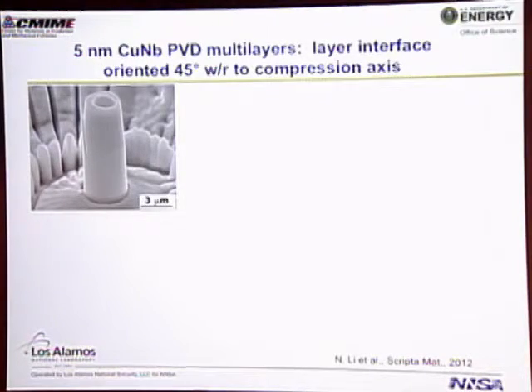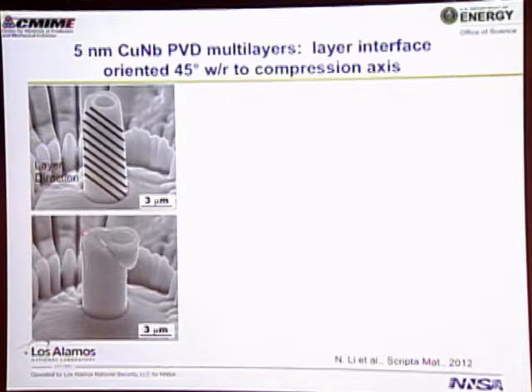So we can test that hypothesis too. We make these layers. We put in our layers at a 45-degree angle. We smush this, and sure enough, they fail right along those interfaces.